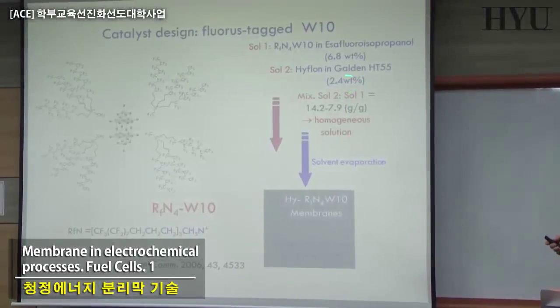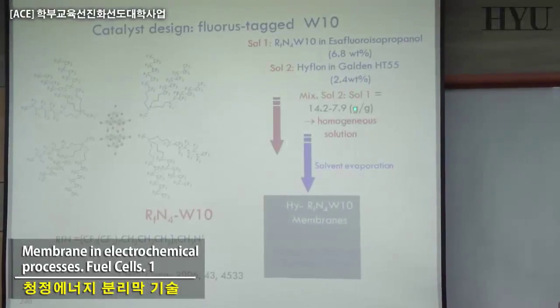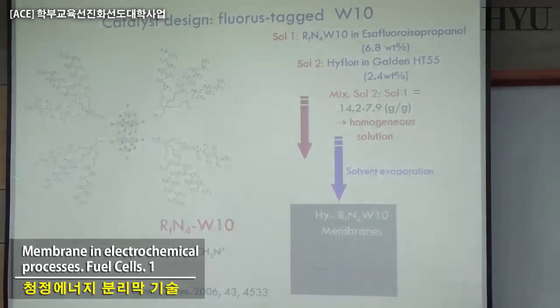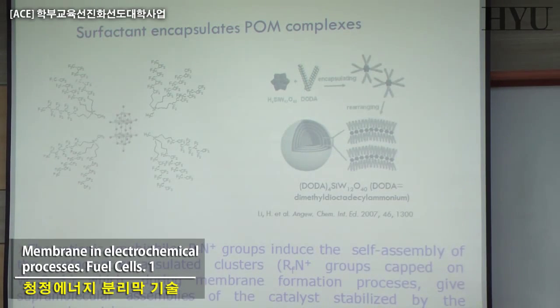So that was done, and this is a kind of recipe for trying to do in this kind of situation. Compared to the results before, as you can see here, the system is relatively changing. The presence of these cationic fluorophilic groups allows a very good dispersion of the catalyst, much better than the one that we were observing before.